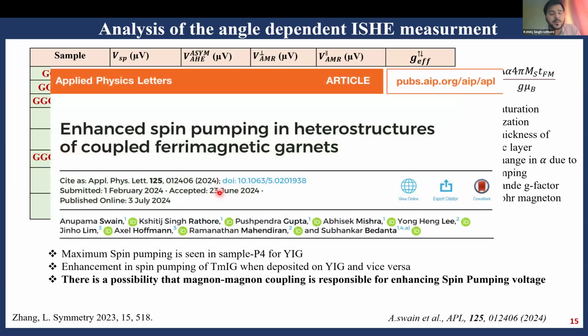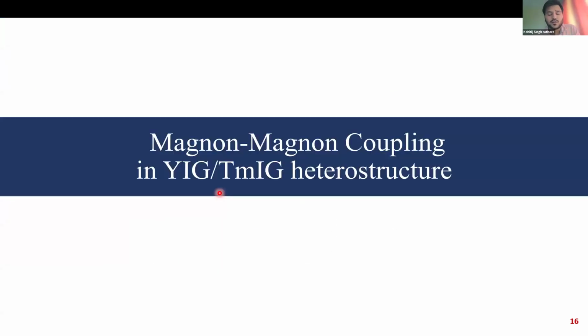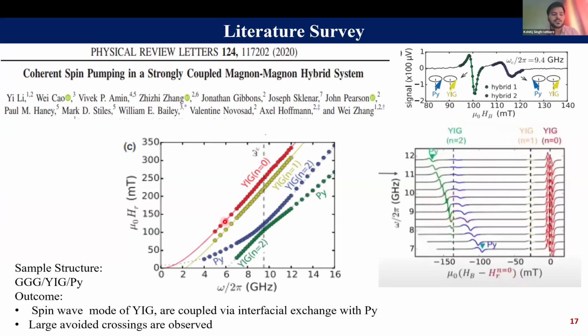This we have recently published in an Applied Physics Letters paper titled Enhancement of Spin Pumping in Heterostructures of Coupled Ferrimagnetic Garnets. Apart from this interfacial exchange coupling, the reason could also be the presence of magnon coupling in our system, for which we did a similar kind of study to what Professor Axel Hoffmann's group recently did with a ferrimagnet and ferromagnet system, YIG and permalloy, where around 9.4 gigahertz the mode of YIG is getting avoided crossing with the mode of permalloy. This avoided crossing region signifies the presence of magnon coupling in the system.